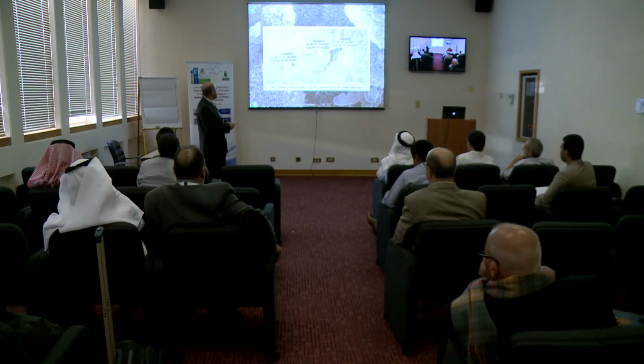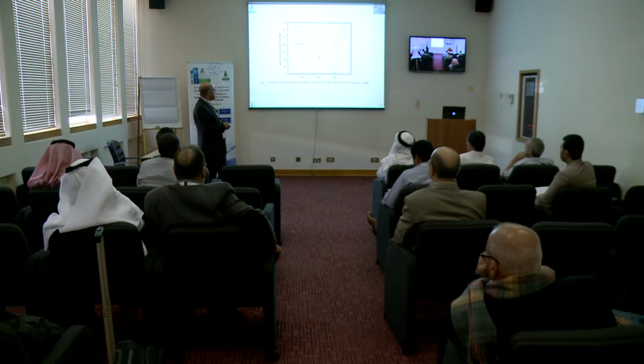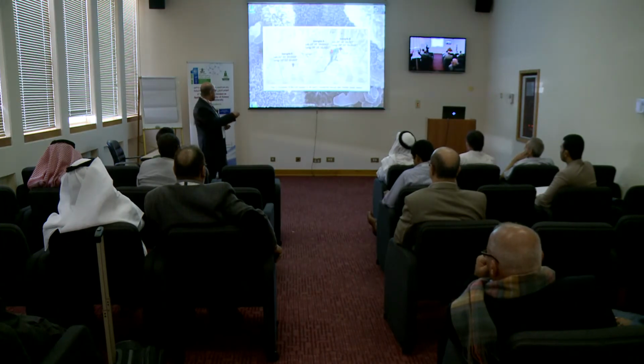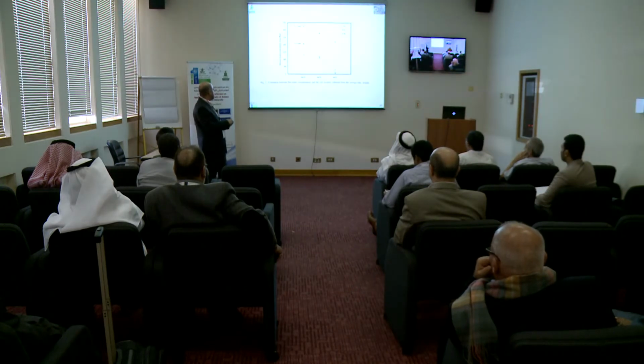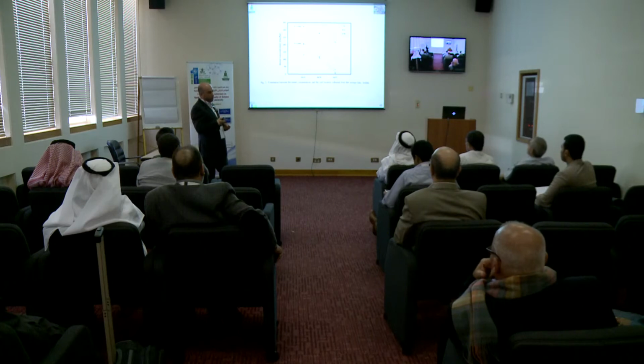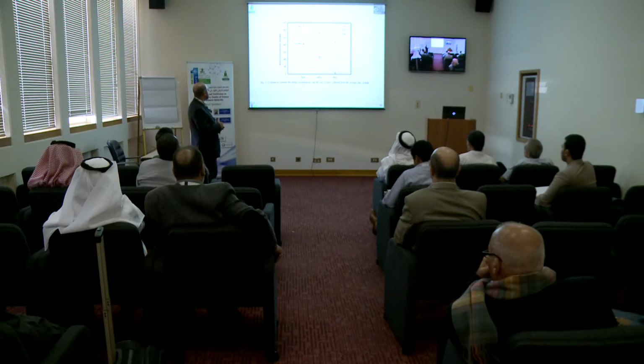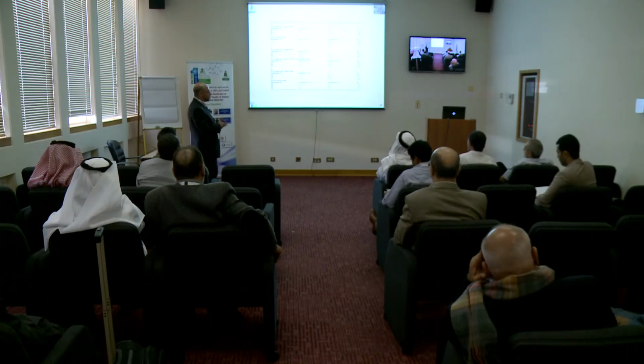Okay, and we found good correlation between the distance from the lake, the main one, and the farthest one. The concentration decreases as we go from one to another one. We found good correlation for arsenic, cobalt, and mercury, and those three are well known as very toxic heavy metals. We studied the removal process, again kinetically and thermodynamically, and we used a leaching process.